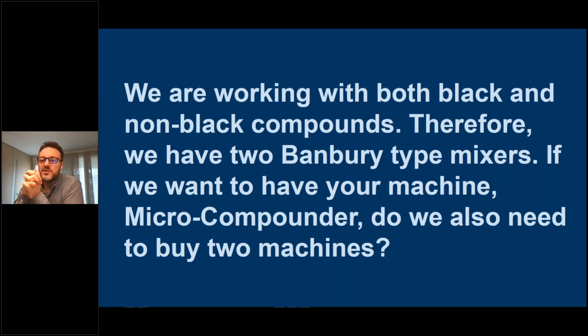Yeah, I understand the question actually, because from my personal experience, once you use carbon black with your instrument, later on cleaning becomes a real issue. If you shift from black compounds to non-black ones, this is a well-known problem at lab scale and also during production. However, in our system, this is prevented by easy cleaning of the machine. Since the barrel is completely closed and feeding can only be done from the top opening, you do not have too much dust contamination problem.